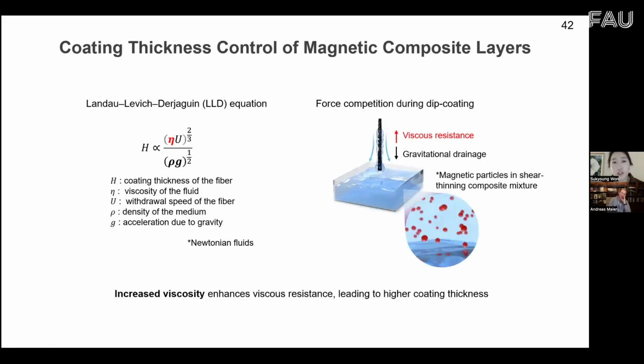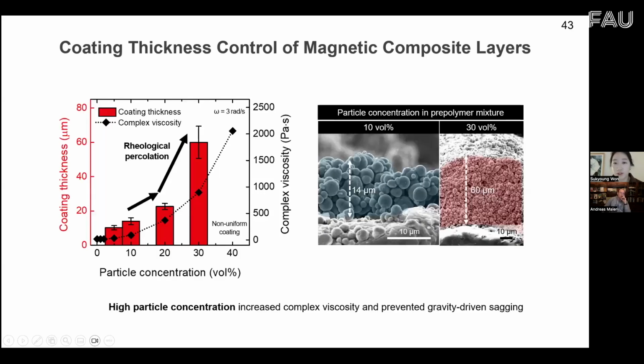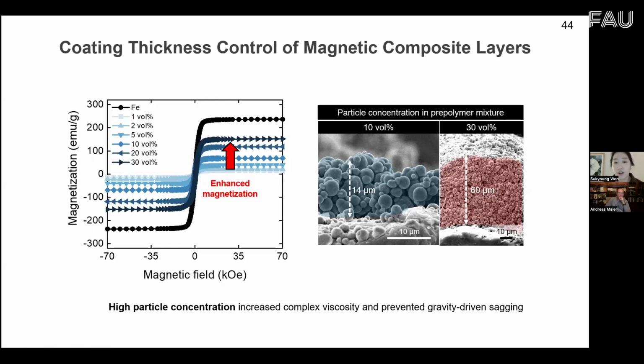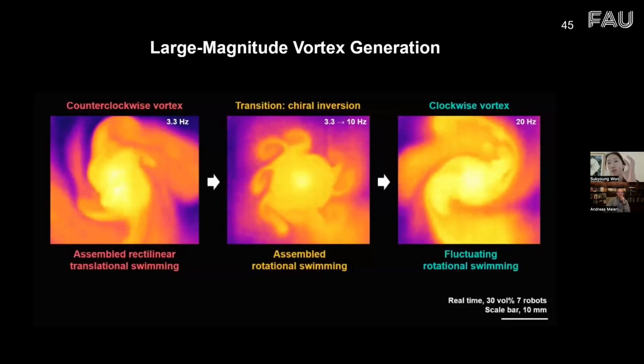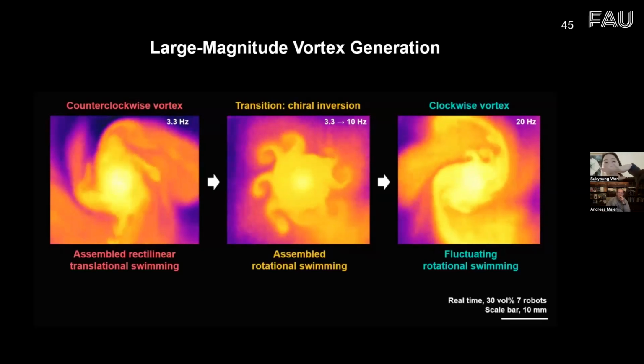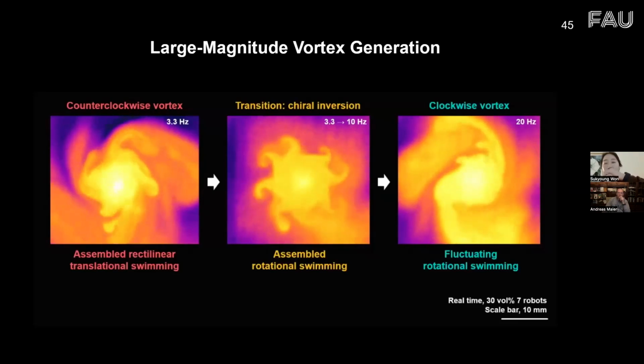And also we can increase the coating thickness of the polymer composites onto the robot surface by increasing the viscous resistance through an increase in the complex viscosity. When we increase the particle concentration during the dip coating process, there was a rheological transition between 20 and 30 volume percent. So we can see a drastic increase in the coating thickness of this magnetic polymer composite on the robot surface. So we can enhance the magnetization of the robots. This increased robot magnetization can interact with the magnetic field underneath the robot, so it intensifies the vortex generation.